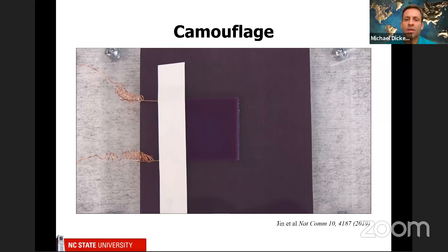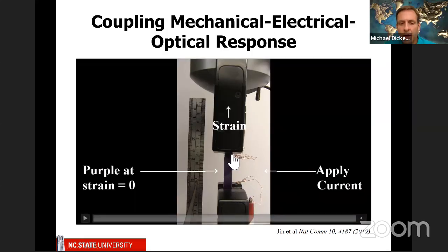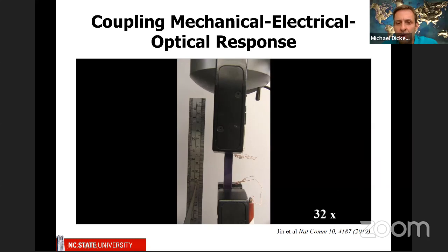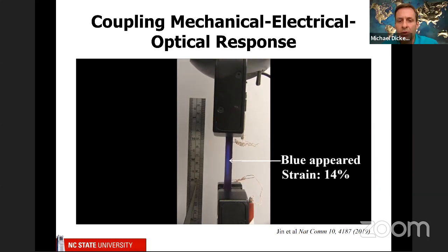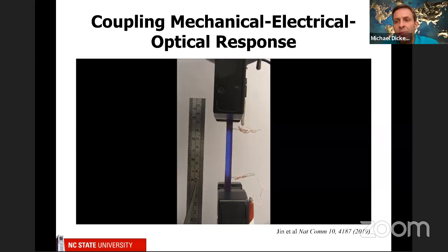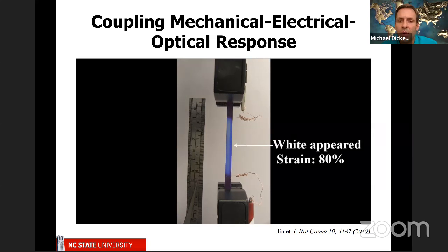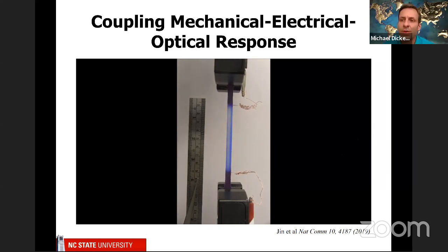Where this gets really interesting is in the following. Here we've got a liquid metal wire that's inside of an elastomer with this purple combination of pigments. There's blue and there's red combined together, so it looks purple. Now, we're going to run current through it, but not enough to change the color. However, when you strain these liquid metal wires, they get longer, but they also get narrower in diameter. And so if you watch this, we're running current through it the whole time, but it's not until you reach a critical strain that it starts changing color. And we can tune where that strain occurs based on the geometry of the wire. So this is a way to give colorimetric indicators of where your strain is at. And this effectively couples mechanical, electrical, and optical properties in a hand-waving sense.